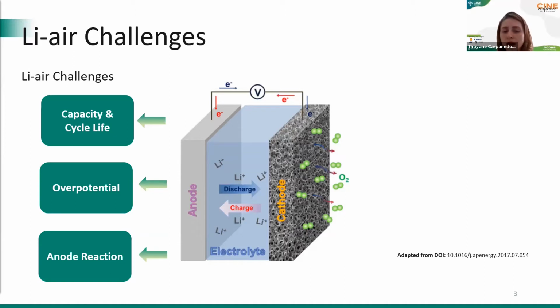And to overcome all these challenges, we usually study the cathode, which is one of the most studied battery components in the literature, focusing on the improvement of oxygen diffusion and the catalytic performance, mainly for the charge reaction. For example, using the metallic catalyst to decrease the overpotential. The anode usually is metallic lithium, although its compatibility with the electrolyte is another issue.